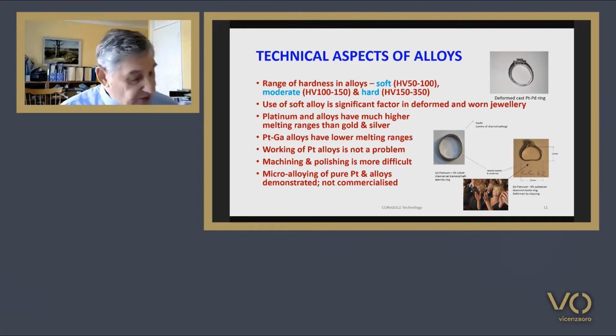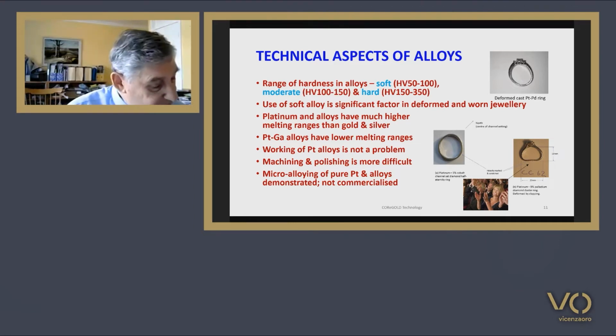Work around the turn of this century has demonstrated that microalloying of pure platinum and its alloys, with small additions of calcium and/or rare earth metals such as cerium, samarium and gadolinium, typically up to about 0.3%, can increase hardness substantially. But such microalloys do not appear to have been commercialized by the jewellery industry, probably because they are not easily cast or recyclable.